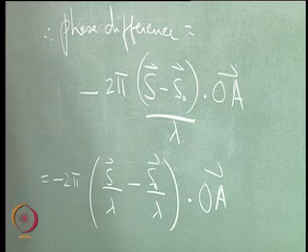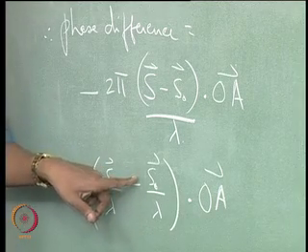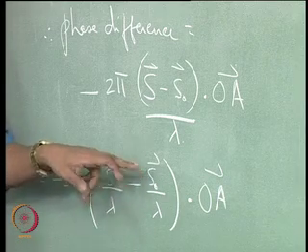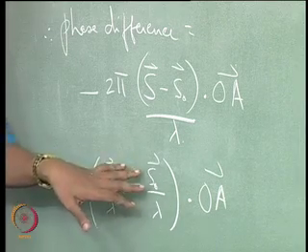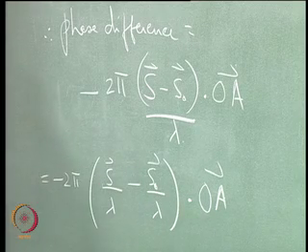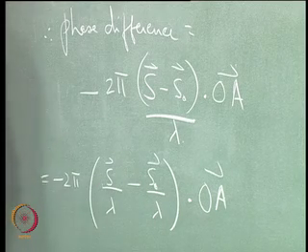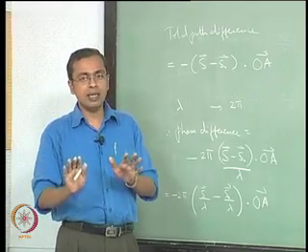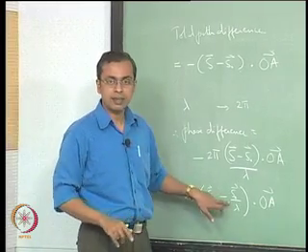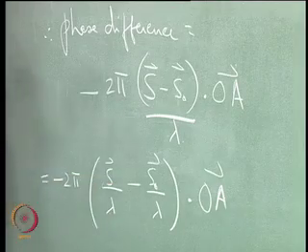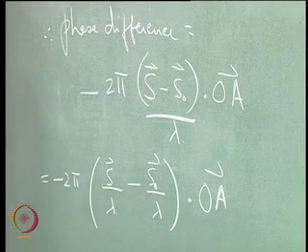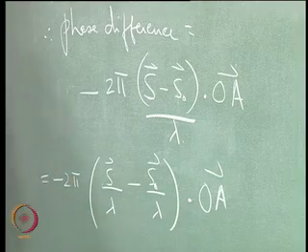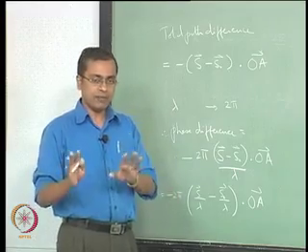You can directly represent it in reciprocal lattice because it has all those attributes: it has the 1 by length convention associated with it and it has a direction. When you say it is a valid reciprocal lattice vector, it has to end at a reciprocal lattice point. Right now we have not yet placed that restriction on this vector, and in a couple of steps I will re-emphasize what I mean by that. Right now it simply has all the attributes to be represented in reciprocal space. So that is the first thing we will note here.